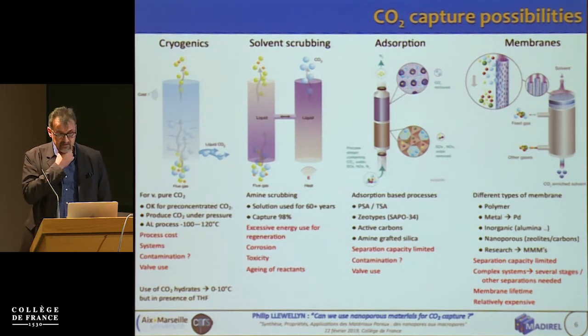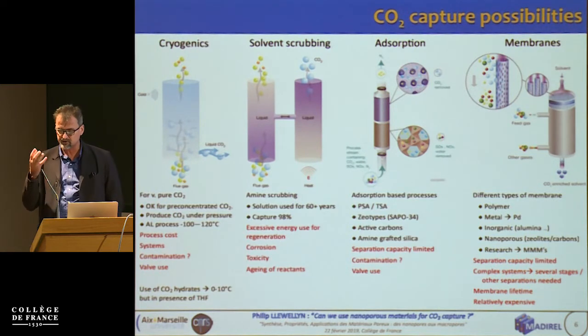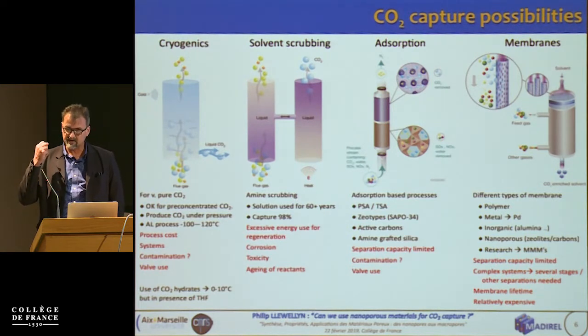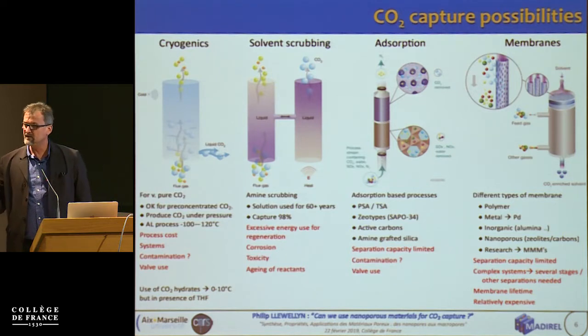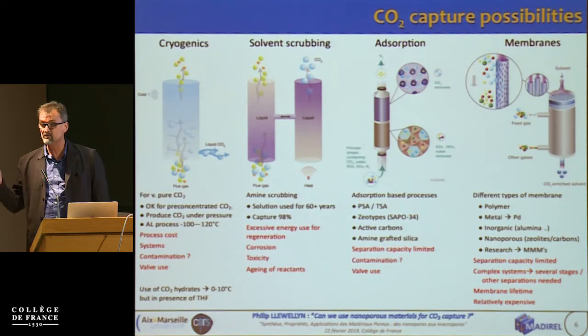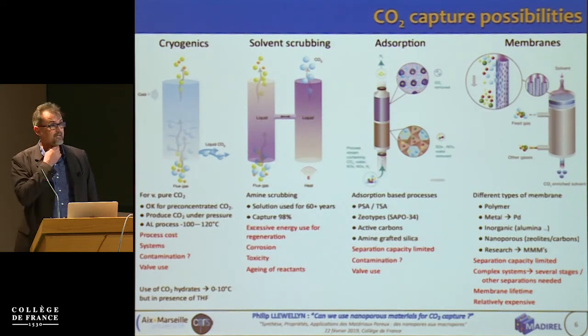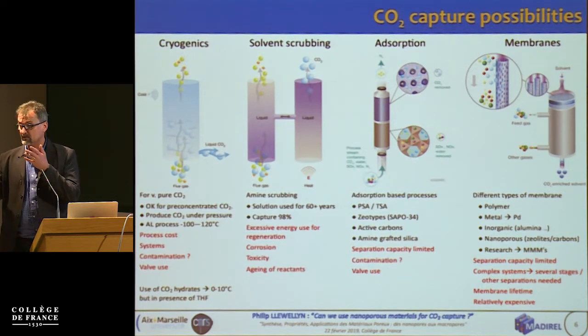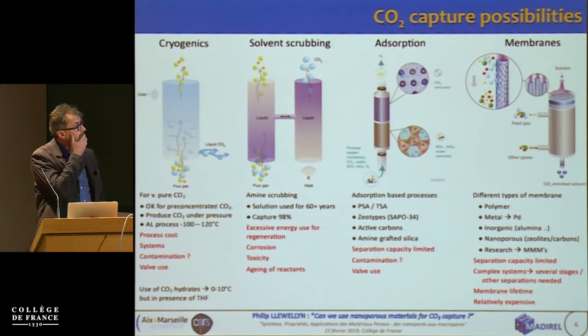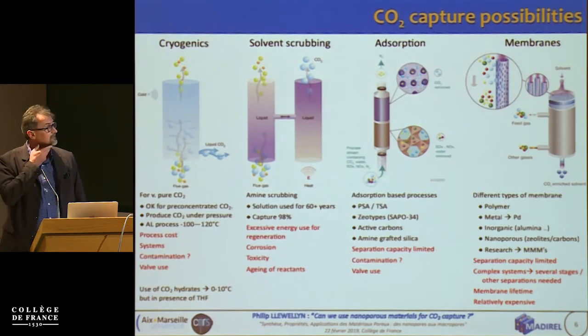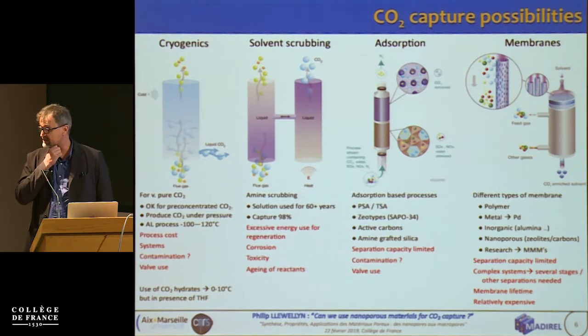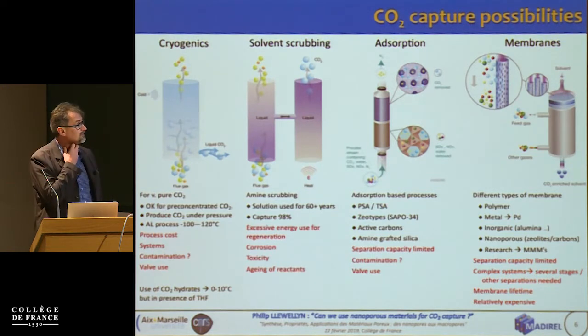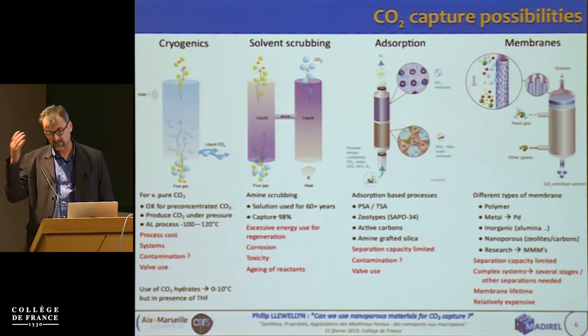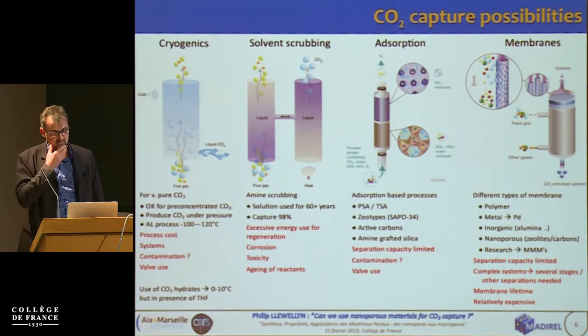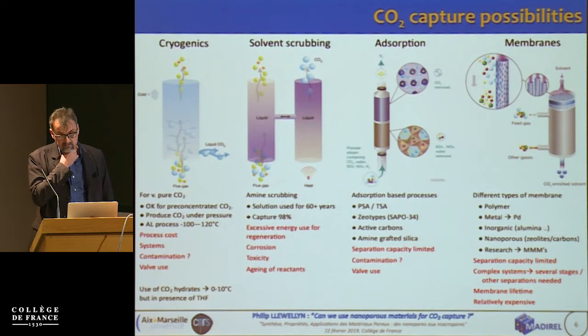But there's an excessive use of energy for regeneration, an awful loss of energy. Because if we have 10 to 15% of amine, it means we have an awful lot of water in the system, which we're heating up when we're regenerating. And we have to heat at over 100 degrees, 140 degrees. So we're just losing energy in heating up the water and cooling it down again. Of course, if we're heating up amines in water, there can be corrosion problems with the amine itself, leading to toxic emissions. And the reactants age, so the thing has to be changed or at least modified every now and again. Then there are two other solutions.